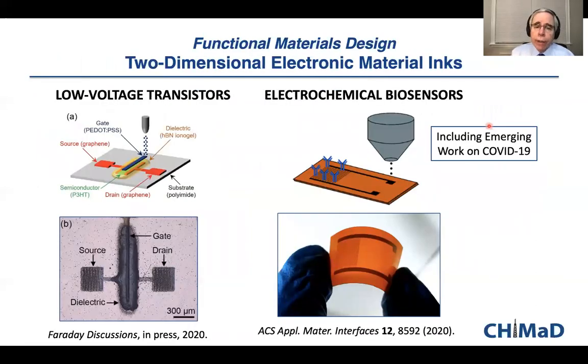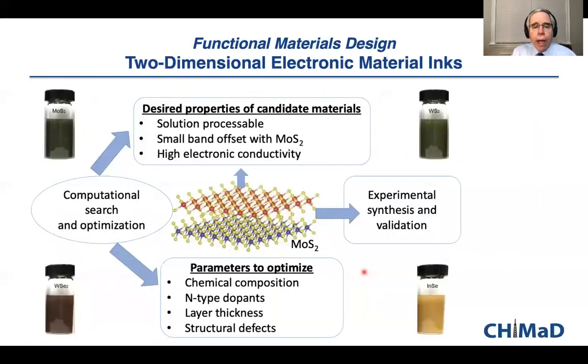Functional materials, we're also looking at two-dimensional electronic inks, in this case, printable low voltage transistors. So the idea here is you have inks with 2D materials in it, and you use an inkjet printer to print electronic devices on, for example, flexible substrates. And the idea is to use computational searches and optimization to understand what the solutions you need in order to be able to process these using, let's say, for example, molybdenum disulfide, which is a standard 2D material. And you're focused on maintaining high electrical conductivity using the chemical composition and layer thicknesses in order to produce these inks. And this is indium selenide, and that's tungsten diselenide.